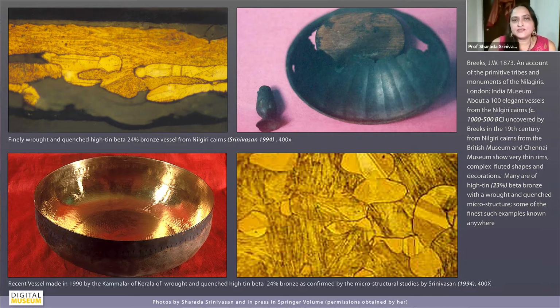So next to that structure of the old Nilgiri vessel, you see this very shiny vessel, which is a new vessel, which I had observed the manufacture of in Kerala. And so you can see there, the base of that vessel shows a smaller diameter of the ingot, the flat ingot, which is then hot forged. The ingot is about 15 centimeters, and then it is extensively hot forged to get this shape of about 30 centimeters or so. And the outer skin, of course, has been left unpolished.